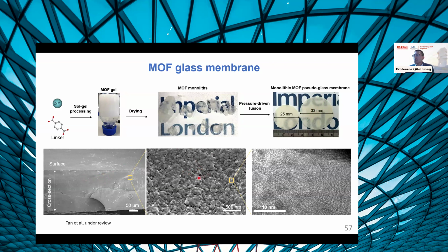When we look at this with high resolution TEM, you can see the crystalline domain surrounded by the amorphous domain. So this shows the presence of both crystalline and amorphous structures in the MOF materials. We believe that these amorphous regions will enhance the selectivity. We did a lot of study of these materials in gas adsorption, and we found that the selectivity of the gas adsorption was enhanced significantly.